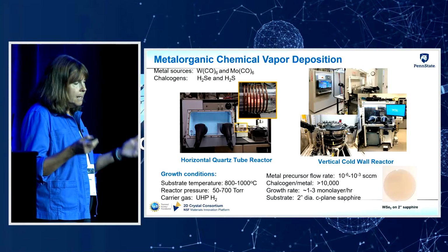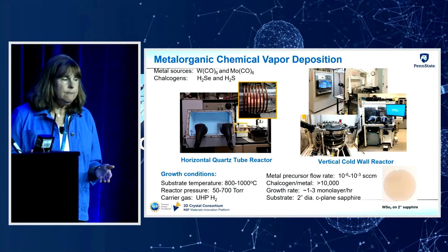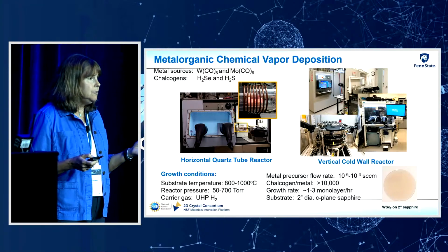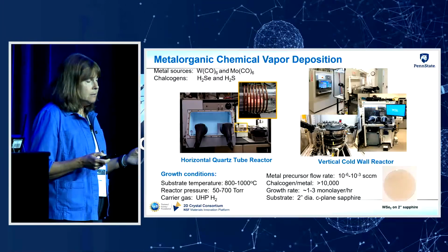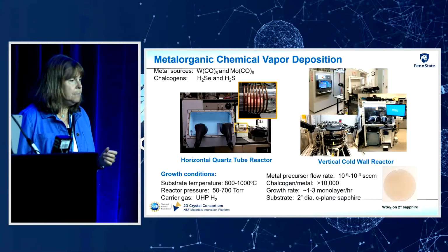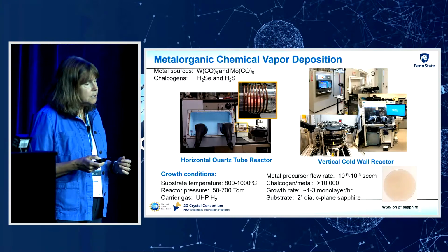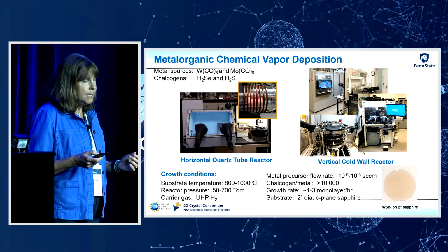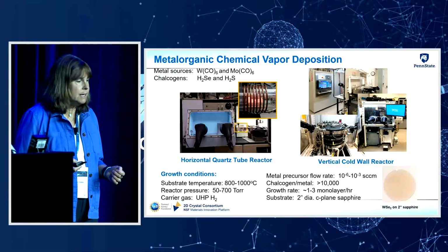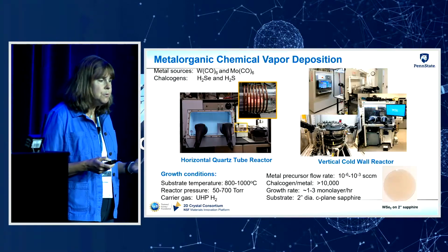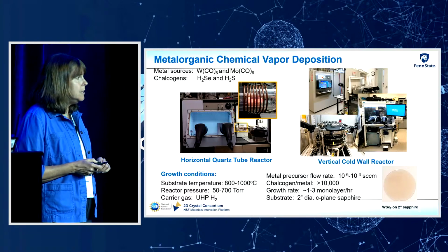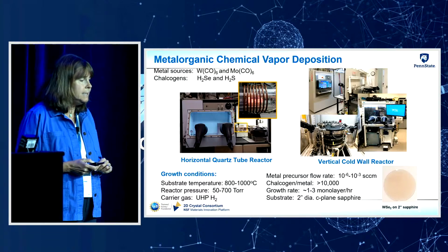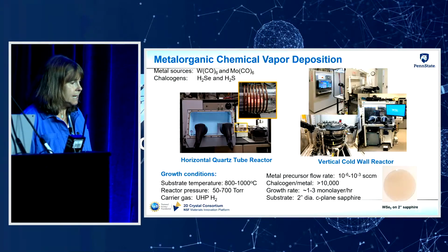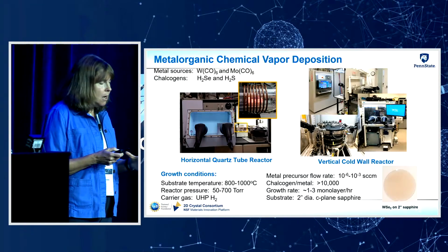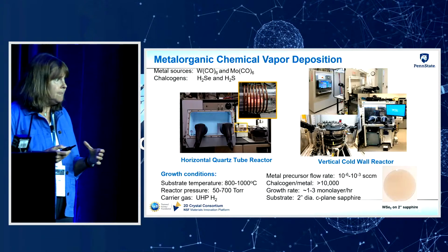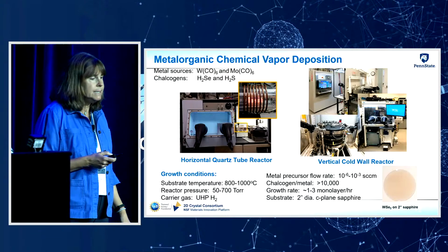So in metal organic chemical vapor deposition, or MOCVD for short, the precursors that we use are metal hexacarbonyls, like tungsten hexacarbonyl and molybdenum hexacarbonyl. And then in our process, we use hydride sources for the chalcogens, hydrogen sulfide and hydrogen selenide. And these are photos of two MOCVD systems that we have in the 2D Crystal Consortium facility at Penn State that we use for TMD epitaxy. They both can accommodate a single 2-inch diameter wafer, so we can grow on wafer scale substrates.